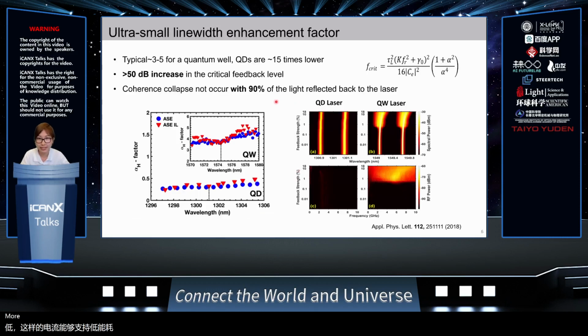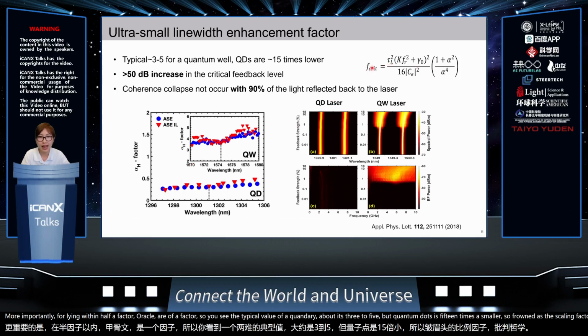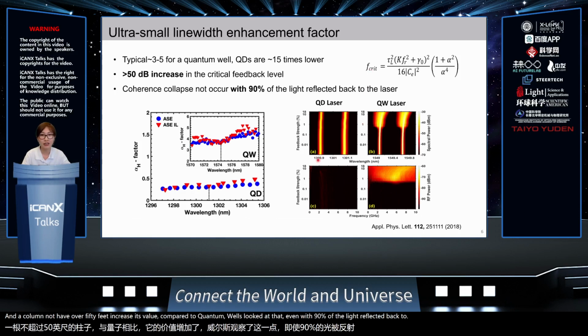More importantly, for the linewidth enhancement factor, or alpha factor, the typical value for quantum wells is 3 to 5. But for quantum dots it is 15 times smaller. From this scaling factor, the critical feedback level is closely related to the alpha factor. Quantum dots had over a 50 dB increase in this value compared to quantum wells, such that even with 90% of the light reflected back to the laser, the optical spectrum shows no coherence collapse. On the contrary, for quantum well devices, complete coherence collapse happens at a low feedback level of -25 dB.